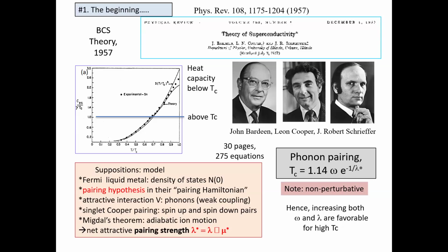And then if this is attractive enough, then the metal will become superconducting at temperatures below Tc. All right. To increase Tc, you would like to both have omega larger and to have lambda larger if you study this equation. And that's not easy to achieve. Scientists have found out over decades that's not as easy to achieve, mainly because when you increase the effective vibrational frequency, this is likely to decrease. So that's something to be challenged.